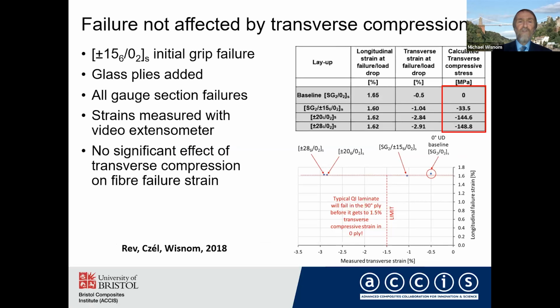And we did indeed get all gauge section failures. What you can see here is that the failure strain in the fiber direction is hardly at all affected by the transverse compression. So we've got very large transverse compression, up to almost 3% here, and yet the failure strain is hardly changed at all.